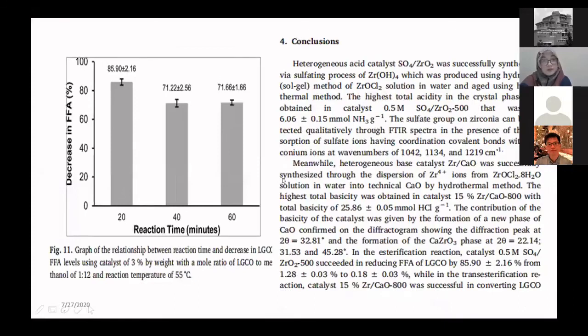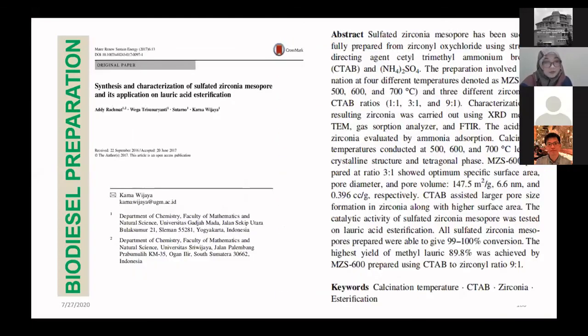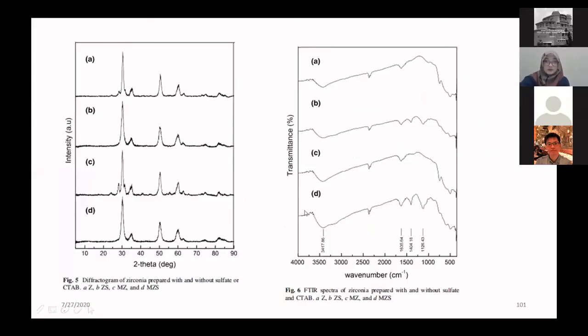Another biodiesel preparation: we have the synthesis of mesoporous sulfated zirconia and its application in lauric acid esterification. We use CTAB as a template to make the mesopores of the zirconia. The template is the material that induces the pores of the material. The application of this material is quite good also.